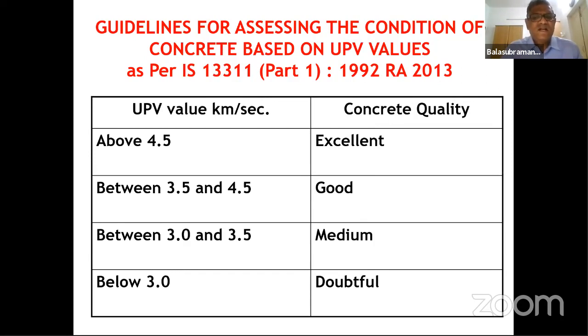So when the velocities are above 3.5, there is no problem. When the velocities are between 3 and 3.5, we found that the grout does not go inside. Generally, the grout does not go inside, and only when the velocities are less than 3 kilometers per second, the grout generally goes in. So it was quite okay.